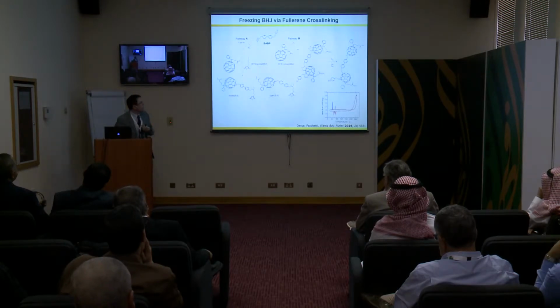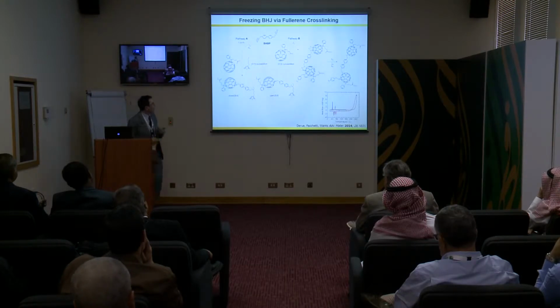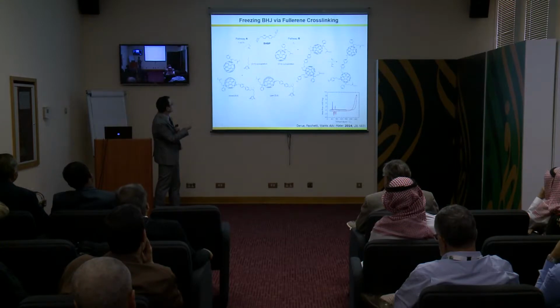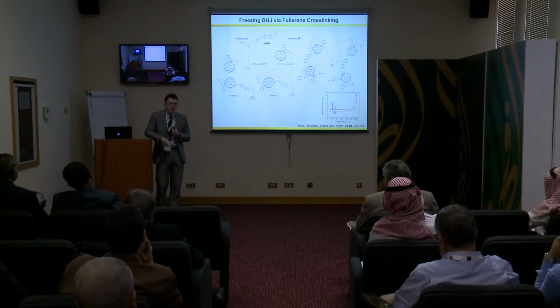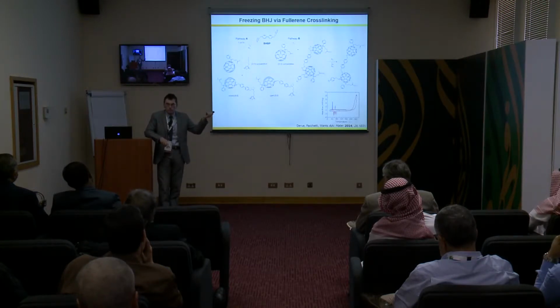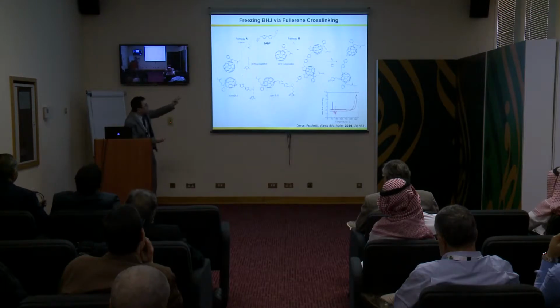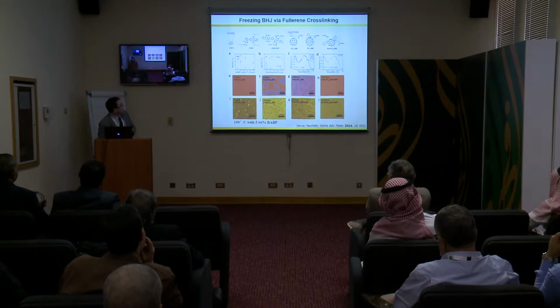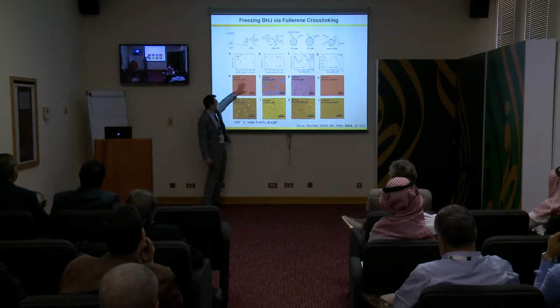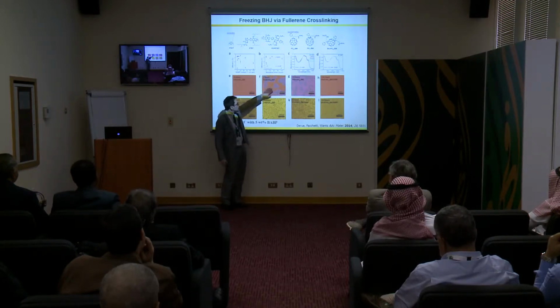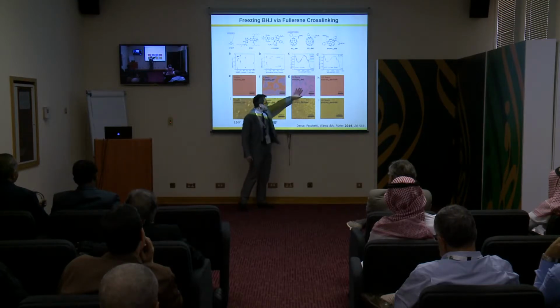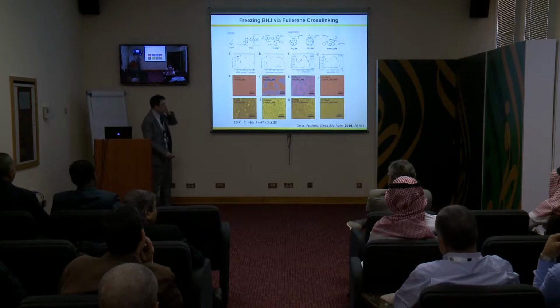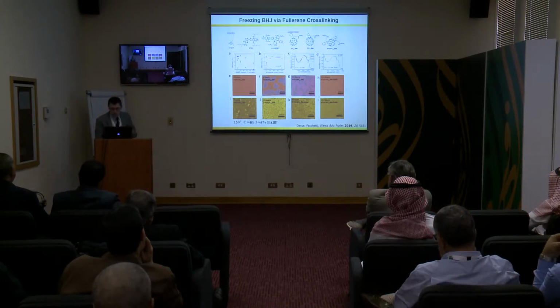So we tried to develop a chemistry which could stabilize the morphology. One of the ways we did it, for those of you who are organic chemists, is using this azide functionality, but with a chemistry which will not form nitrene. We don't want to form nitrene, but we want a chemistry which goes through the formation of aziridine type of chemistry. It's something which we could achieve using this type of cross-linker. When you take a blend and start warming it up, you have this huge phase separation, so the efficiency of this cell decreases dramatically. When you start cross-linking the blend, the efficiency of this cell remains much more stable. So this is one of the approaches we have taken to try to stabilize the morphology.